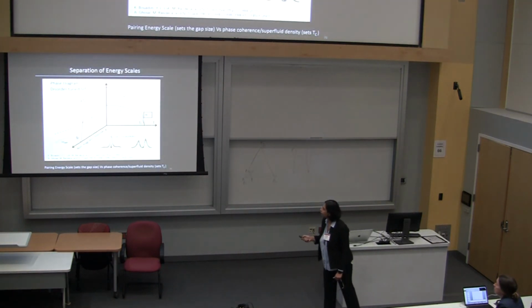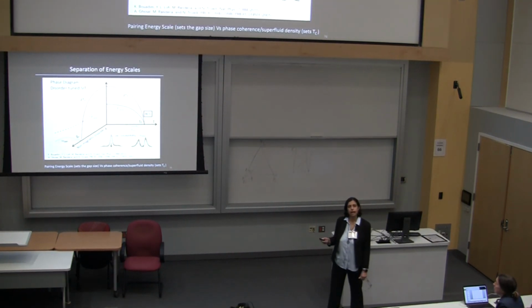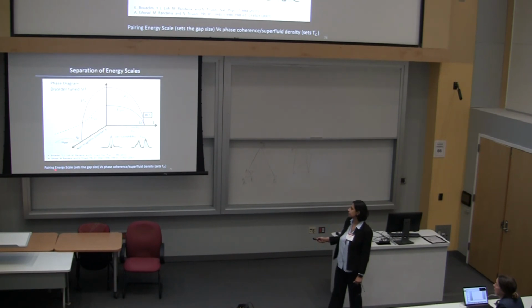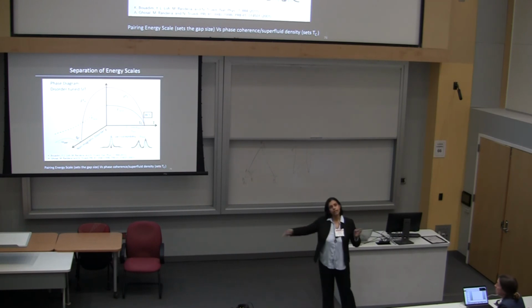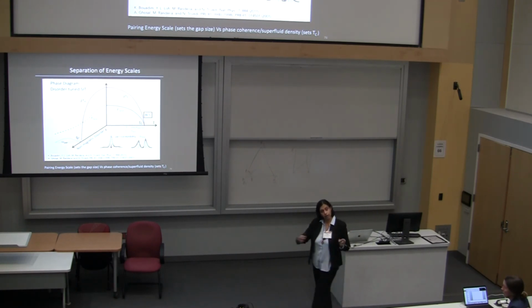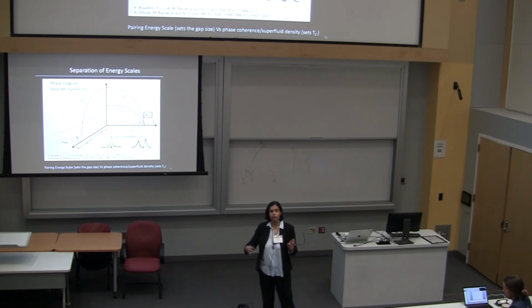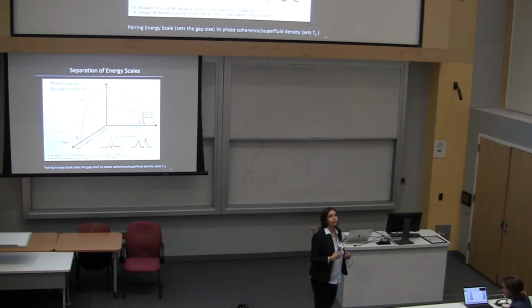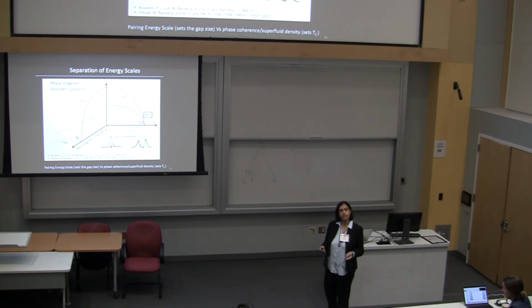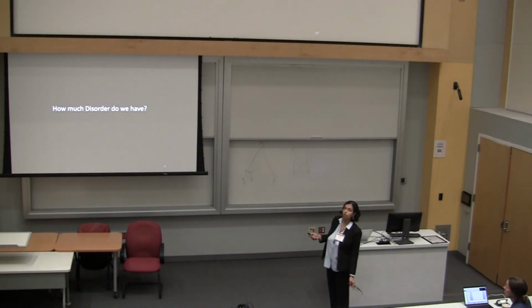One thing people have known in the past is that if you can separate these two energy scales, which is the pairing energy scale, which sets the gap size, from the phase coherence or superfluid energy scale, which sets Tc, then you can have a situation where you get a pseudogap. And this happens, for example, if you introduce disorder. So the simple question to ask is, is our sample disordered? And how much disorder do we have?